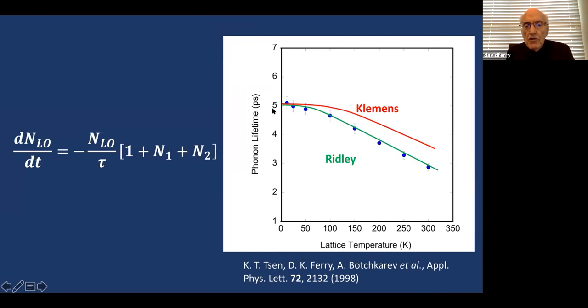And you can see in gallium nitride, the phonon lifetime varies from 5 picoseconds at a few Kelvin to a little less than 3 picoseconds at room temperature. Now it's worse than that because the nitrides have this very unholy property, which we've discovered in HEMTs and heavily doped stuff, that this lifetime is dependent upon the population of the electrons. The lifetime gets shorter as the electron density gets higher. And we don't understand that. At least I don't understand that.